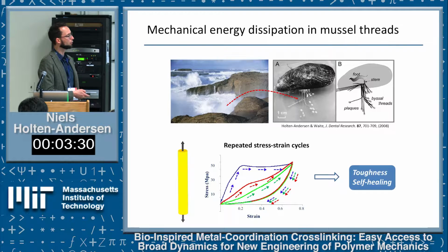What's interesting is if you pull on it a second time, whatever gave it its original mechanical stiffness is now broken during this yield point, and it's much softer. However, if you let the material rest underwater at room temperature for about an hour, it begins to get stiff again—the slope gets high again, the yield point begins creeping back in, and if you wait long enough, the whole material will completely recover.